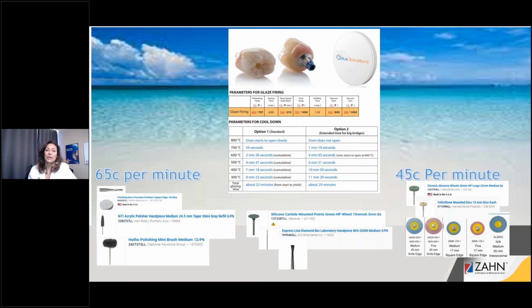In the middle of the screen there on the bottom, you'll see the silicone mounted wheel. That wheel is super, super, super thin and flexible. So if you do have, say, a large bridge or a really aesthetic case and you want to do some characterizing in the Green State, that's a wonderful tool to get in approximally, because again, I know I've mentioned a million times, we don't want to take a diamond disc and go in approximally, open up those embrasures after zirconia has been sintered. You're going to create microfractures that will lead to the restoration failing in the end. So that tool's been just a lifesaver.